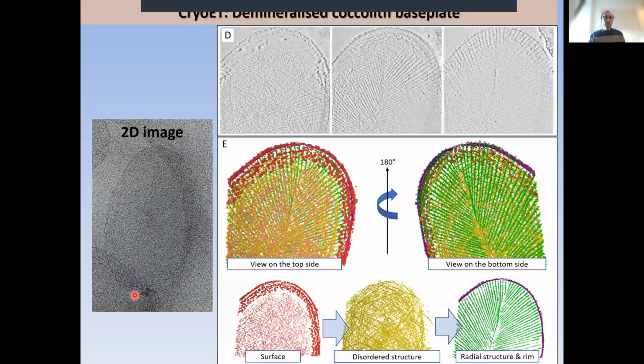And the first thing that we did was cryo-electron tomography, which is a technique to do imaging in 3D using the transmission electron microscope. If anyone wants to hear more, I can explain. And we did that on the base plate, and we could see that the base plate actually has a much more complex structure than it looks like just from this image. I mean, it has this kind of a three-layer structure that is comprised of fibers of different thickness. What is in green here, which I'll call the bottom, is made of cellulose fibers. It's very organized, but we don't know yet what these other disordered structures are made of.